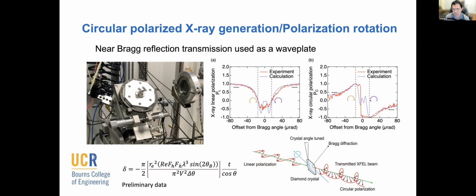We suspect the difficulty is coming from working with a beam that has been through a high energy resolution monochromator. It's also possible that the narrow bandwidth of the beam, which is in the meV energy resolution, makes it difficult to work with. But after several trials, we were able to get it working reliably.